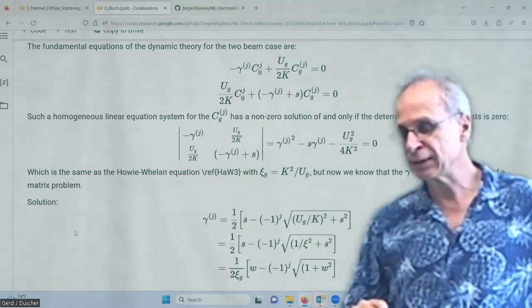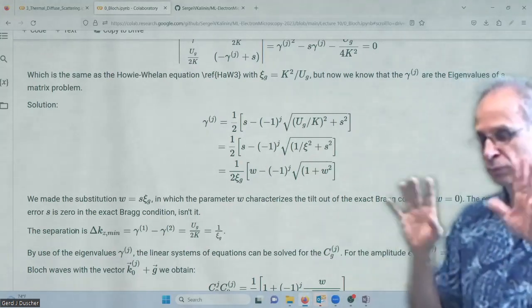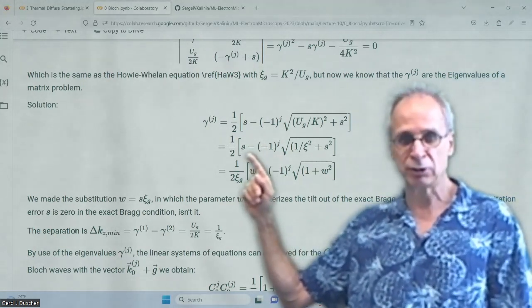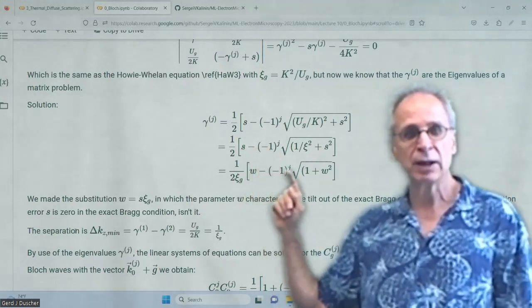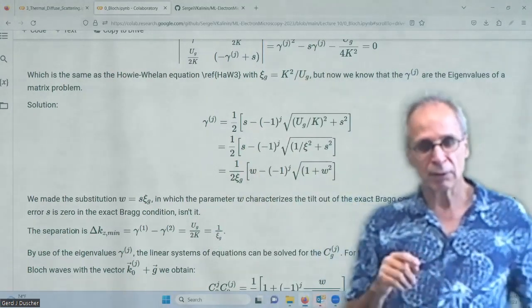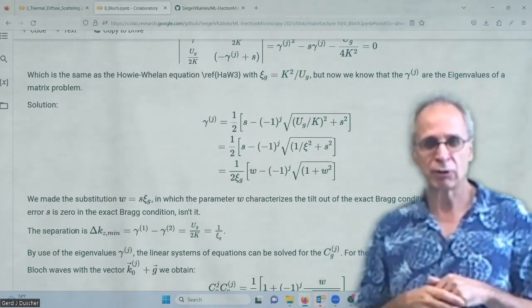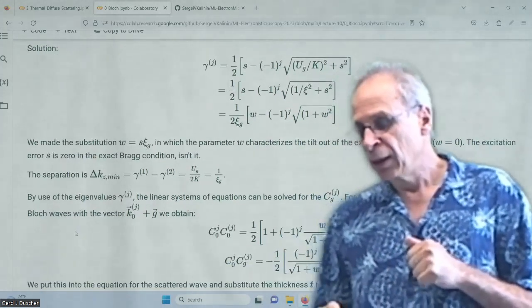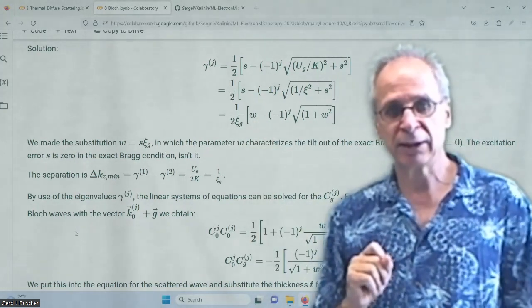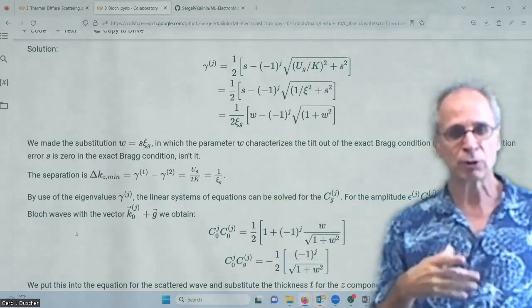We have a solution for that — it's a quadratic term, so we have two solutions. After some manipulation, we have S — which is actually our excitation error introduced in previous lectures. We have an extinction distance, which is the periodicity between the diffracted beam changing intensity from having zero to having full intensity. We have another substitution — an effective excitation error — that makes writing easier and is often used. Either of these equations is what you will find in books on Bethe theory.